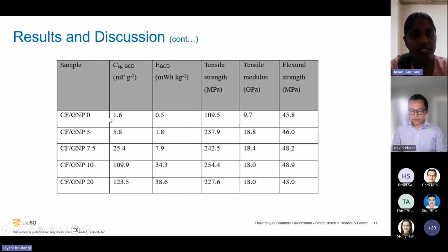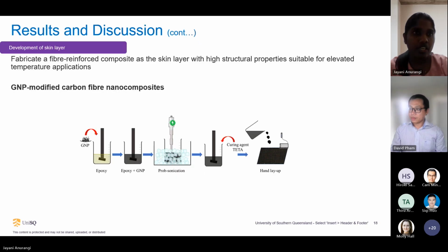According to this table, you can see almost all properties, capacitance, energy density, tensile, and flexural, have improved after GNP coating. My next objective was to fabricate a fiber reinforced composite as the skin layer with high structural properties suitable for elevated temperature applications. In this research, I developed a GNP modified carbon fiber nanocomposite.